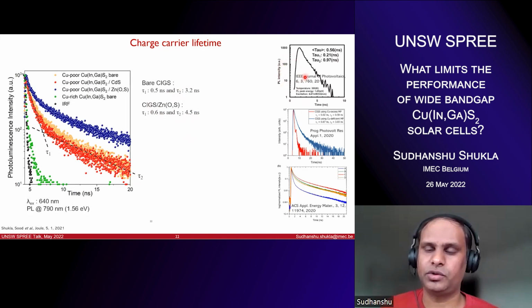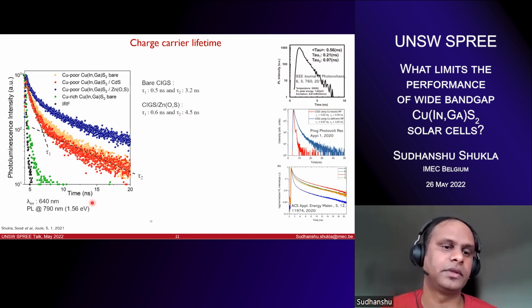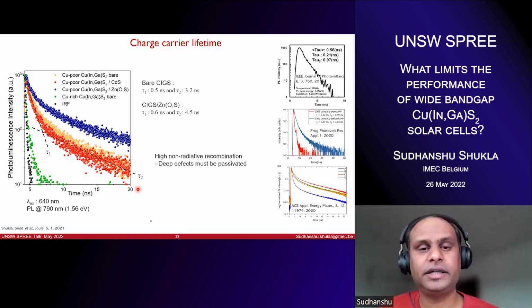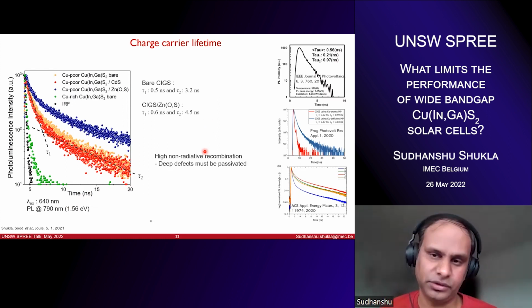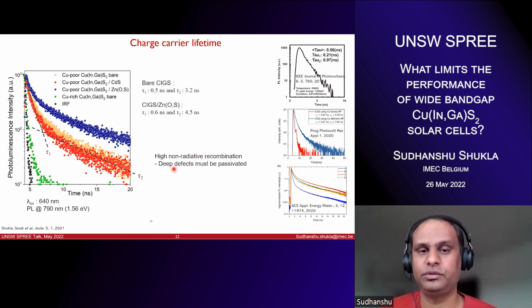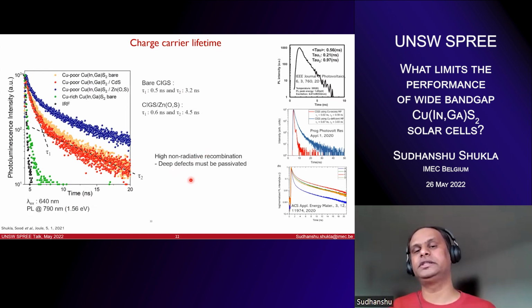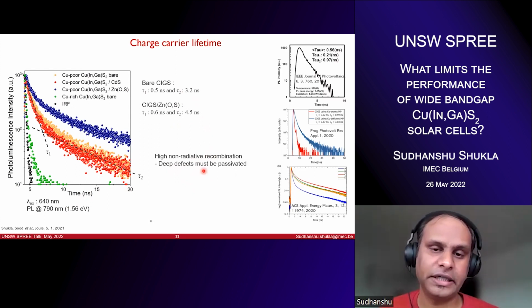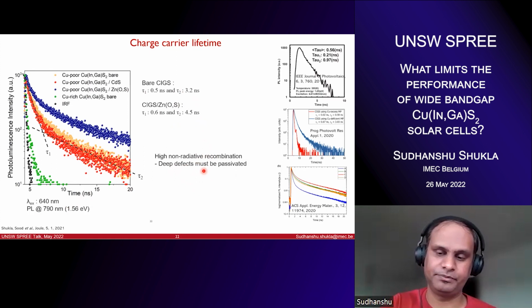The highest, or the record absorber, so to speak, has an average lifetime of about 0.6, and here it's slightly higher than that. Although I think taking this kind of averaging of the lifetime makes no sense as such, because these are two different physical processes happening, and taking the average doesn't actually tell you anything, but for the sake of comparison, it's okay. And so the bottom line here is that you have a very high non-radiative recombination. Even if your quasi-Fermi level splitting is high, these values are not at all good for a good PV material. So they have to be solved. To do that, the first step should be to address these deep defects. So unless you passivate these deep defects, these lifetimes are not going to get improved, because it's ultimately the non-radiative recombination through these deep defects that is limiting it.